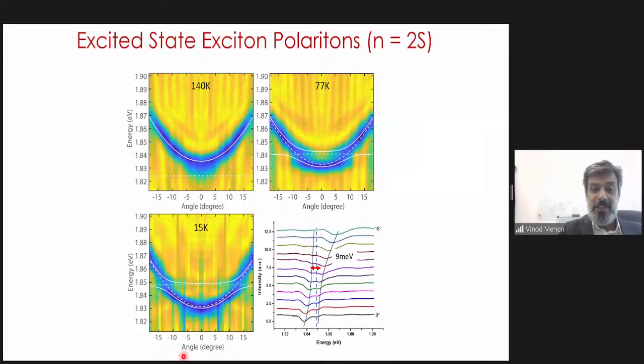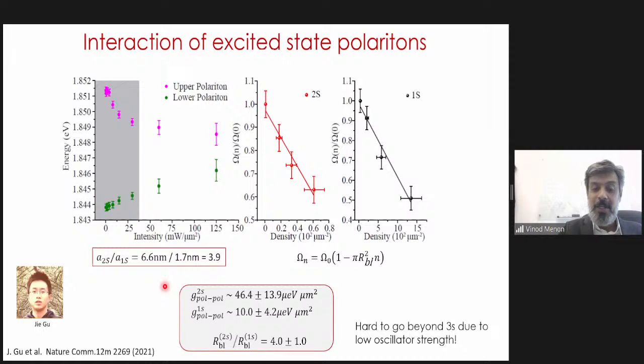So what we see here is that as you cool the system down and as you drive the 2s exciton into the thing, you get strong coupling. But really what the main result of this experiment was to show what happens with nonlinearity. So we pump the system harder and you watch what happens to the polariton branches. And from that, we can extract the effective Rydberg radius that the interaction happens over, and you see the 2s versus 1s.